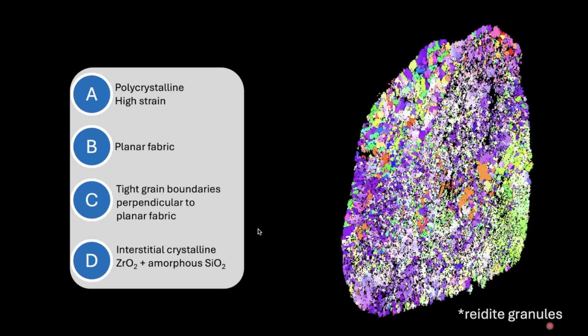If you made Reidite and then you back transformed, most samples of Reidite that we have experimentally and naturally are lamellar. So they have a planar fabric, and you kind of expect that you would sometimes preserve that planar fabric if you back transformed from the Reidite, even if you turned into granules. The high strain would make sense if it's a completely solid state transition. Those tight grain boundaries also make sense.